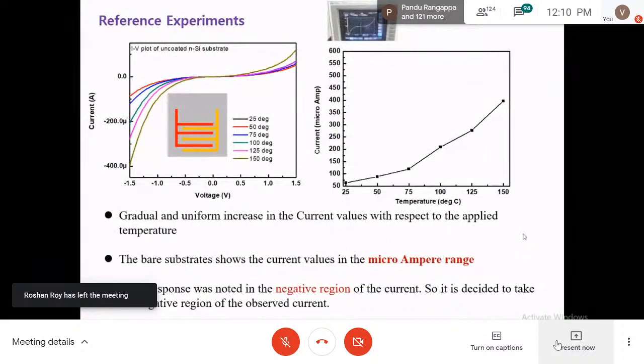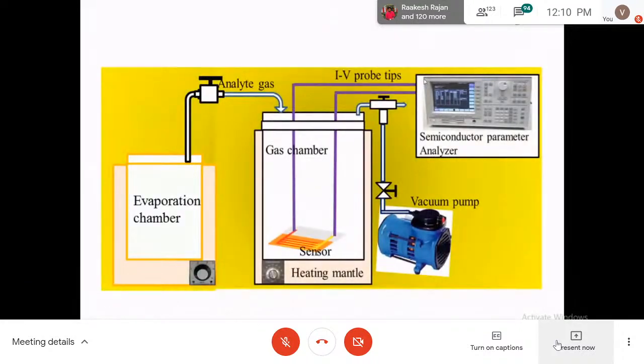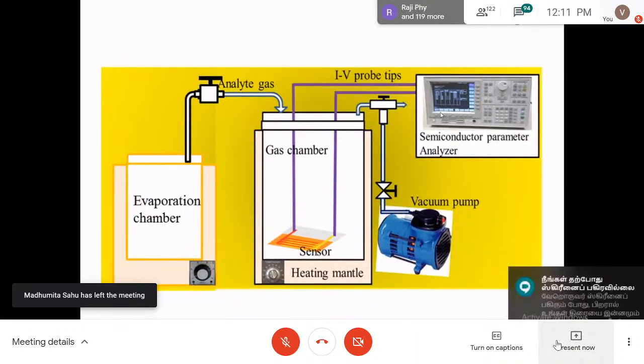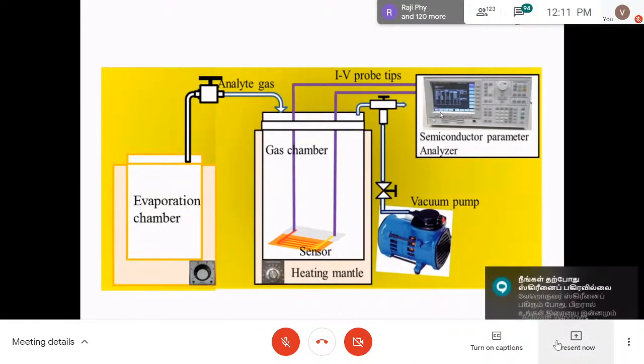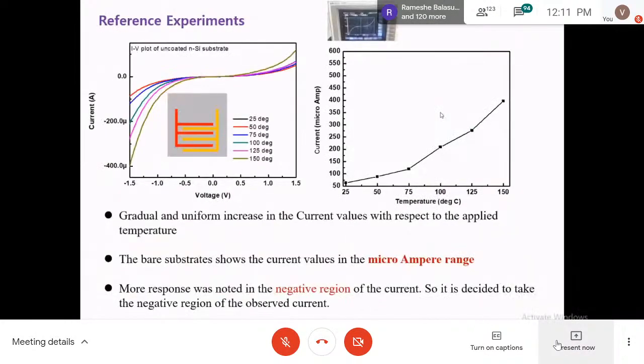Okay. So far we have prepared and characterized the coating. We tried to use cyclohexane in the PCVD on the sensor element, and then we have to go for the actual experiments. First of all, we look at the electrical response of the as-prepared sensor without introducing any gases. We used just the cyclohexane coated sensor. This is the semiconductor parameter analyzer. We have to connect the sensor lead with this parameter analyzer, and then measure the current and voltage properties, IV or VI properties.